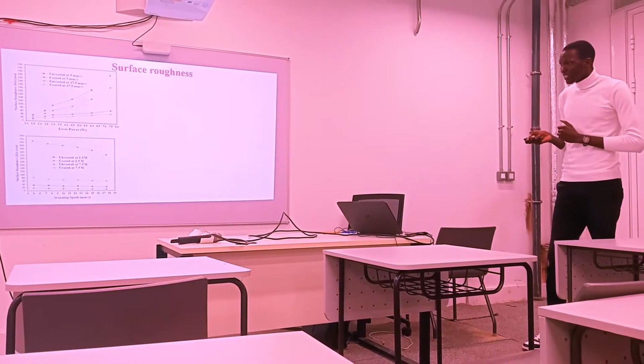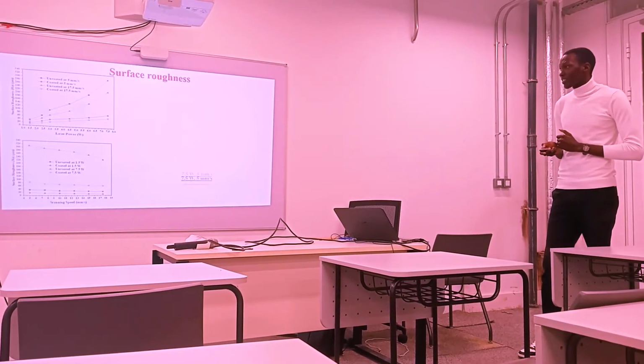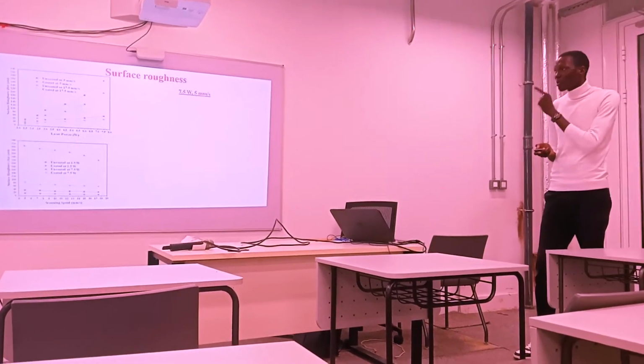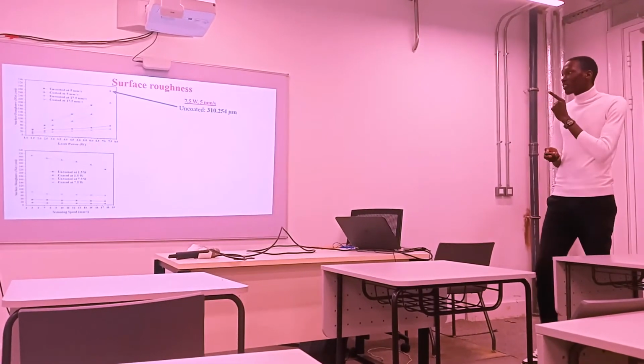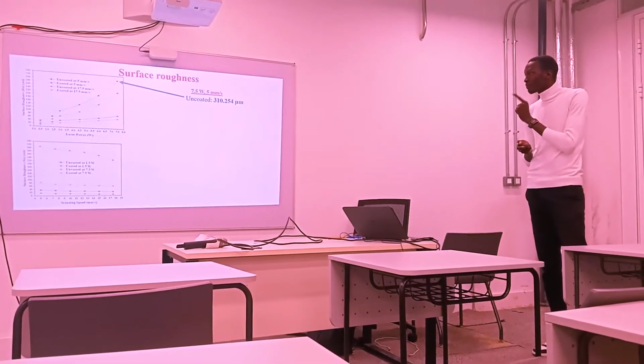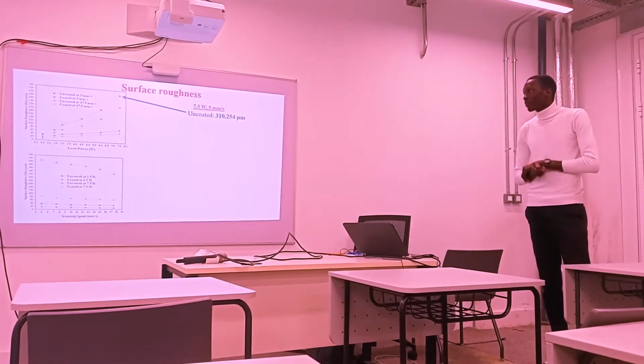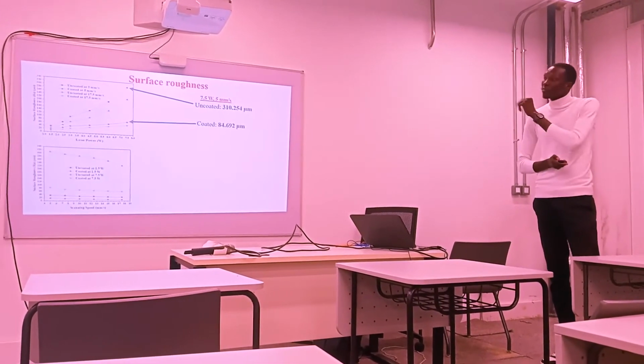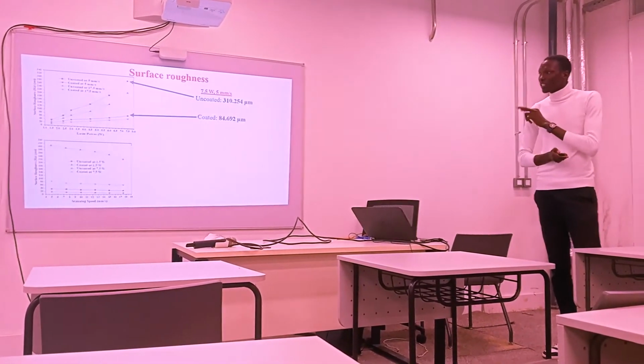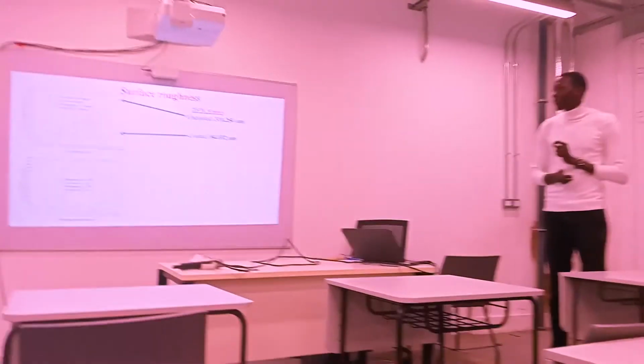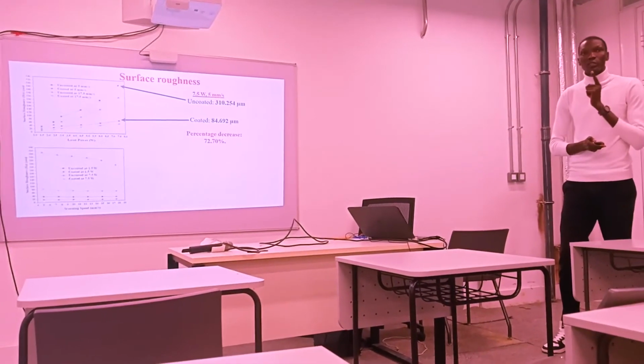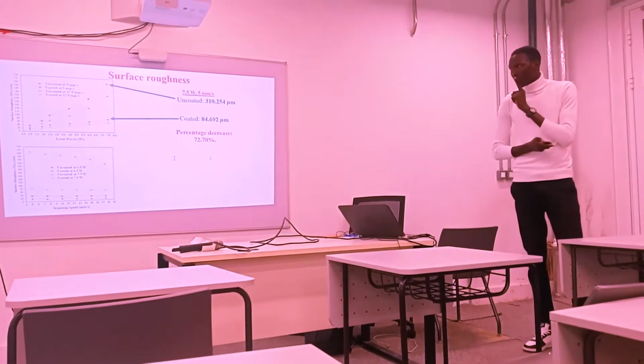Then scanning speed and surface roughness. At maximum power and minimum speed, we got the values for the uncoated sample to be 310.254 micrometers average surface roughness. For the coated, the value decreased to 84.692 micrometers, a percentage decrease of 72.70%.